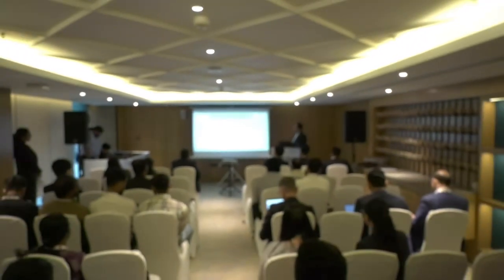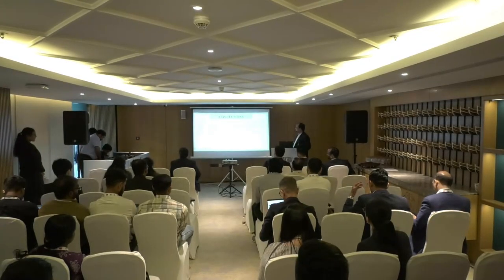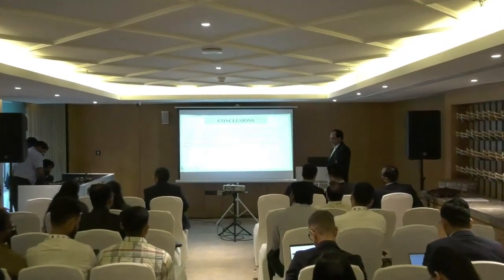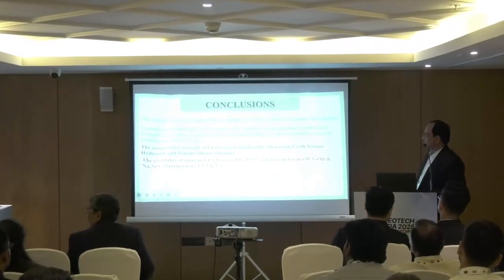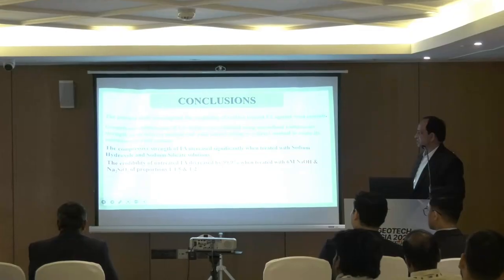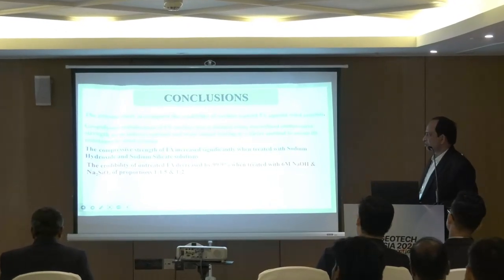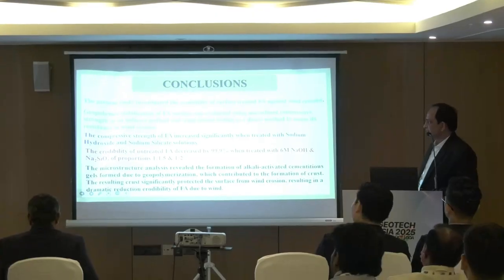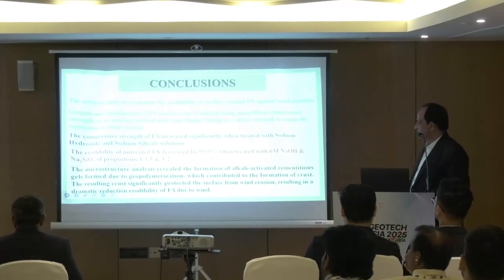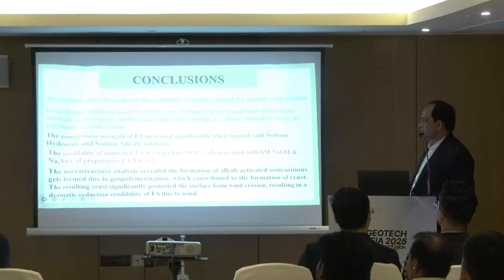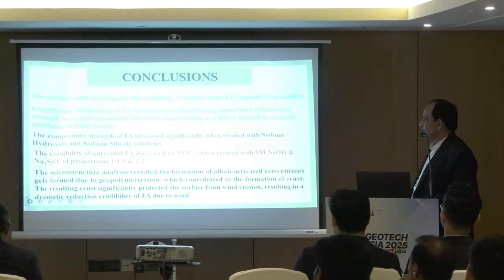So coming to the conclusions, the present study investigated the erodibility of surface treated fly ash against wind erosion. The geopolymer stabilization of fly ash was evaluated using UCS as an indirect method and wind tunnel testing as a direct method to assess the erosion aspects of fly ash. The compressive strength increased significantly when treated with sodium hydroxide and sodium silicate. Friends, the erodibility of untreated fly ash decreased by 99%, which is remarkable, when treated with 6 molar, of course, with different proportions of sodium silicate. Finally, the microstructure analysis revealed the formation of alkali-activated cementitious gels formed due to geopolymerization, which contributed to the formation of the crust.